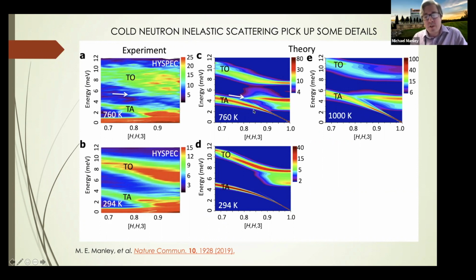The other problem is with the calculation in general. For example, just the normal phonon, the transverse acoustic phonon, is much too high. And I think that's preventing this whole branch from appearing completely flat. There was a shift in intensity. If you go to higher temperatures, you start to recover that. So there's still some work to be done. But I will say that this calculation is done without any control. It's first principles based. You just let it go and you see what you get. And so the fact that it could tell us where to look and find localization was great.